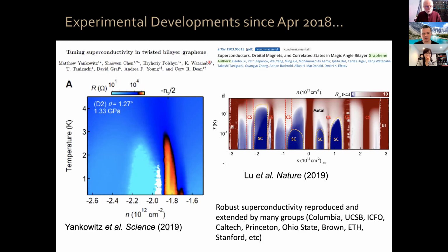The first two papers to reproduce our results: the first one was a collaboration between the group of Cory Dean at Columbia University and Andrea Young at UC Santa Barbara, where they were able to not only reproduce our results, but tune the superconductivity with pressure, and confirm that it is indeed associated with the presence of those flat bands. And then the second group to reproduce our results was the group of Dmitri Efetov, where they saw that in one device they could measure additional superconducting domes.